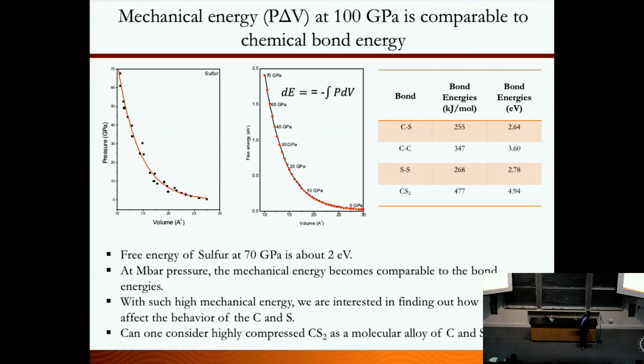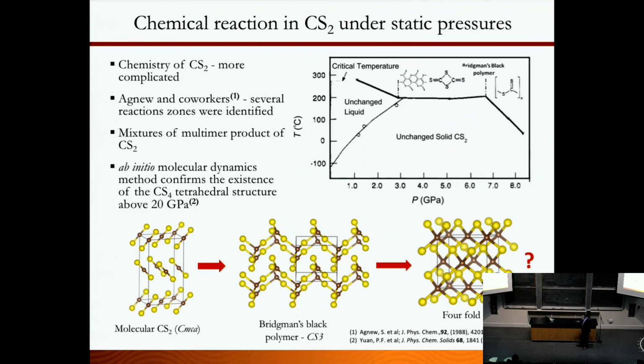By applying pressure, going to a pressure of 100 GPa, you're really tuning the bond length, the energy of this bond. If you look at carbon and sulfur, it's 2.6 electron volts, carbon-carbon 3.6, sulfur 2.7. So you're really tuning the bond energies. So can we use this to make a highly compressed sample like carbon disulfide? Is it going to be like a molecular alloy of carbon and sulfur? In terms of mechanical energy transformed into tuning the chemical bond, it's an interesting material to subject.